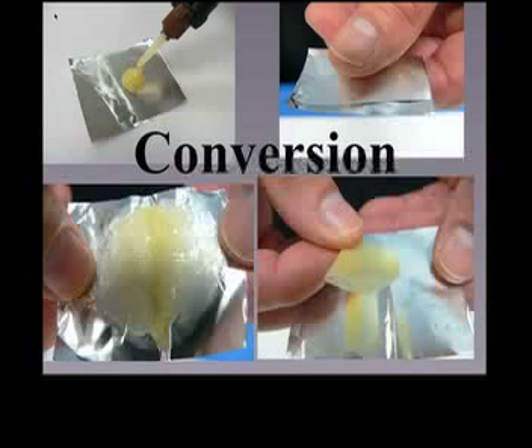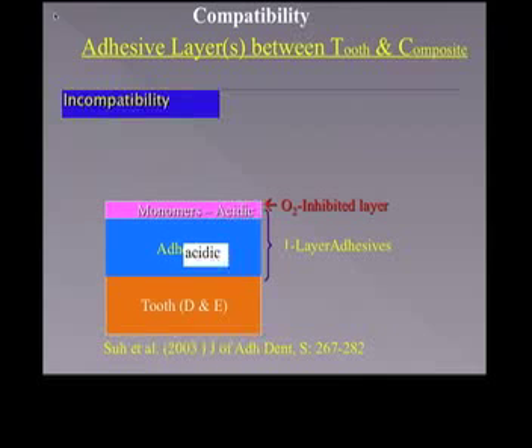Incompatibility ranges from totally incompatible to less than optimal, and it's defined by our bond strength. Incompatibility is a function of pH of the oxygen inhibiting layer. This tertiary amine is considered a base and is neutralized by the acidity of the oxygen inhibiting layer.